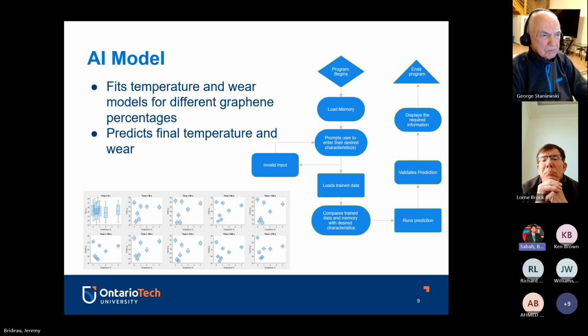Okay. To answer the softening question first, our goal is obviously not to change the characteristics of the grease. However, there is a slight softening effect, but the effects of the actual enhanced grease itself outweigh that effect. So you're giving up one thing in order to improve two others, if that makes sense. And the base grease we used was actually Lucas Oil's white lithium grease. It was the one with the least amount of additives that we could find, because making our own pure grease in-house is not really possible or realistic. So it was the closest one with the least amount of additives and variability in its formula.